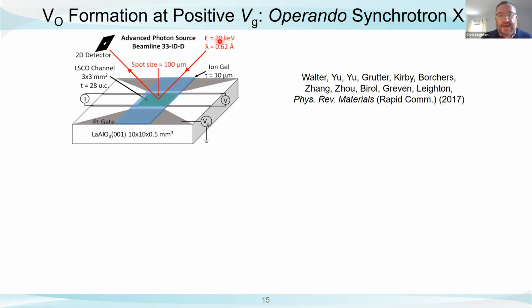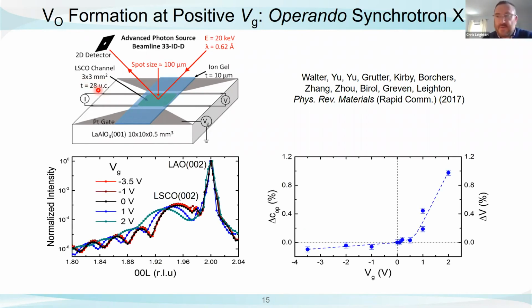So here we're using high energy X-rays. It's very easy to penetrate tens of micron thick ion gels. We can scatter from films that have thicknesses, let's say 28 unit cells, and get enormous signals. And we can do very simple experiments like specular X-ray diffraction. So this shows here the LSCO film peak, now measured in situ as a function of the gate voltage.